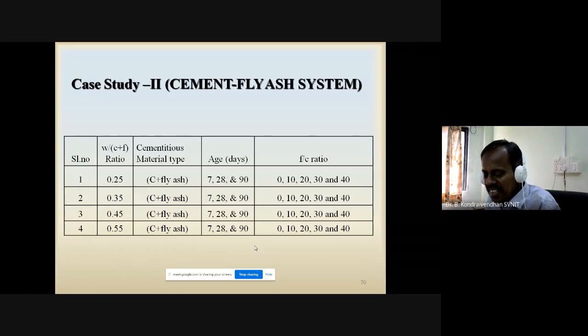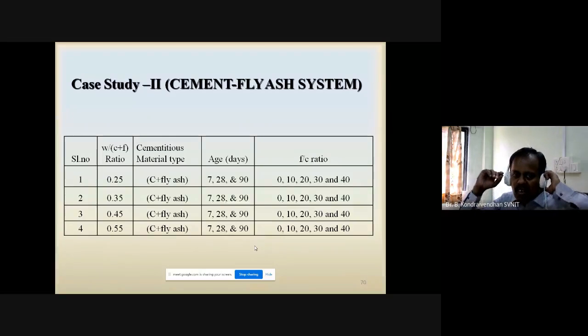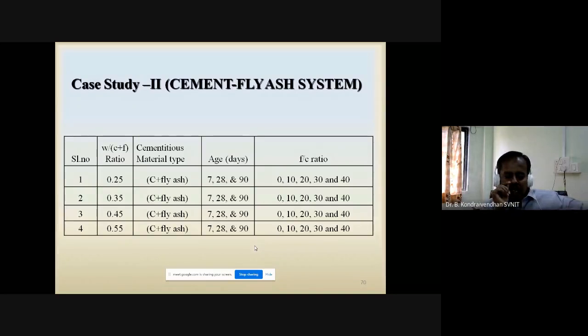So that's why I started with only OPC paste. Now I am coming to the cement fly ash system. Here we use different water cement ratios, that is water by binder ratio: 0.25, 0.35, 0.45, and 0.55. We use the cement fly ash, and curing age is varied: 7, 28, and 90 days.